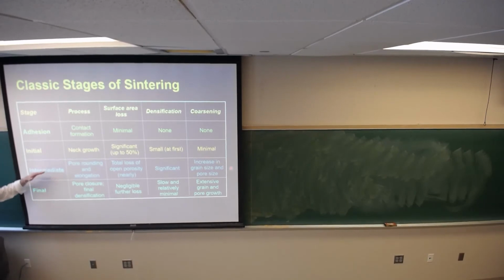And this transition from intermediate to final occurs around 88 to 90%, okay, of the density of the body. Okay, so when you're at 88% density, above that level, we consider the pores to be closed and no longer continuous and connected to the outside. Where does that 88% come from? 88% comes from what's called a percolation threshold. Particles in suspension at 12 volume percent will form a continuous network through the suspension. Okay, we call that a percolation threshold, and by comparison, when the pore volumes are less than 12%, we consider them to be no longer continuously connected. Okay, the pores change shape.